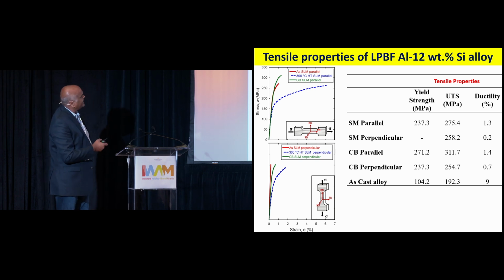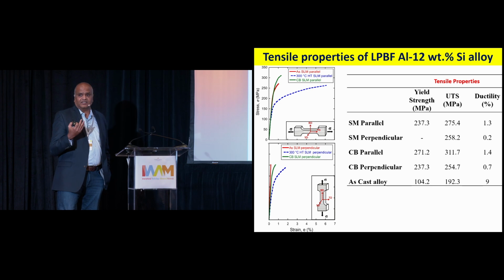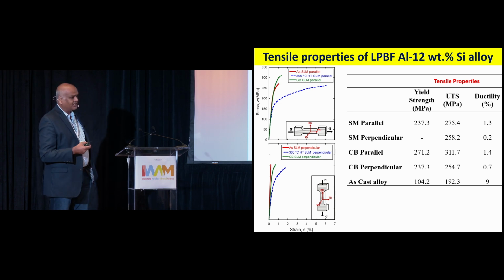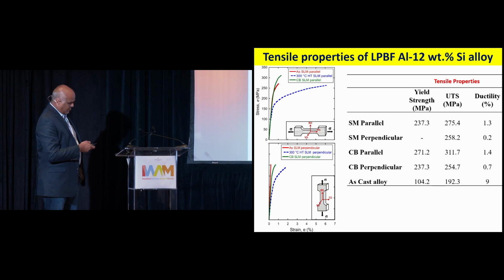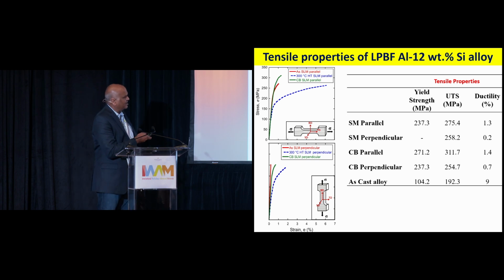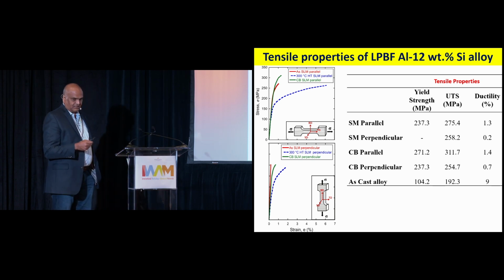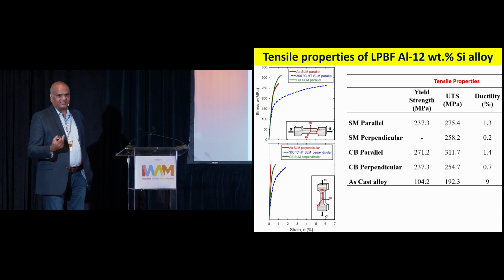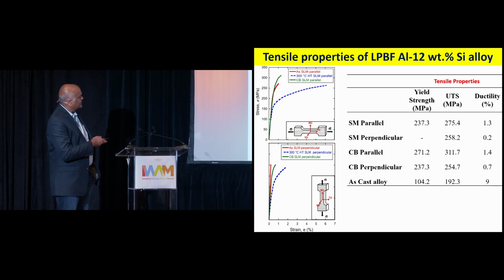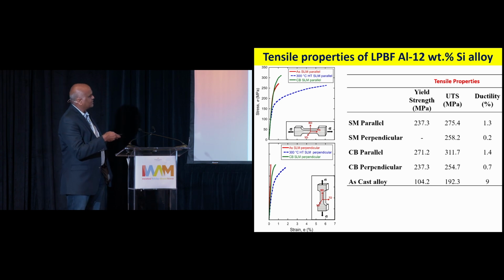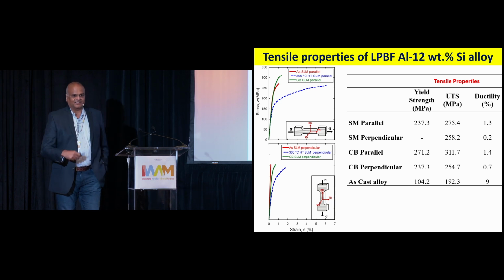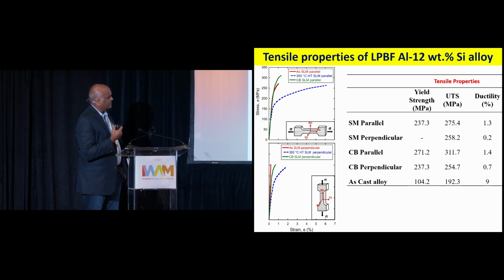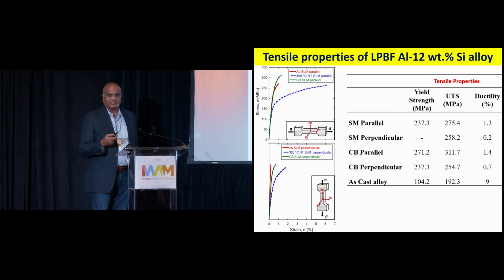So we take one of these alloys—if you consider car engines, most of these are aluminum-silicon alloys near eutectic composition. If you take this alloy and just use casting, the yield strength will be about 100 MPa, tensile strength about 200 MPa, with reasonable ductility of about 10%. The same alloy, made into powder and 3D printed using laser powder bed fusion—you'll notice the strength has more than doubled, from 100 to 200 plus. The UTS has also gone up, but the ductility has really tanked. It's gone very, very bad. So the strength goes up when you 3D print an alloy, but the ductility comes down.